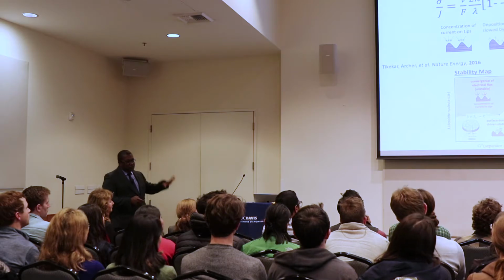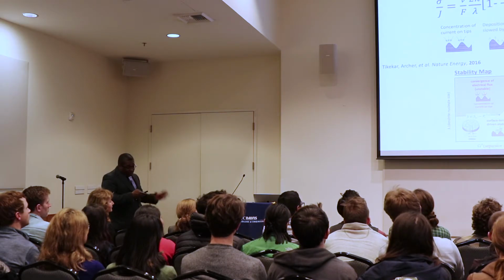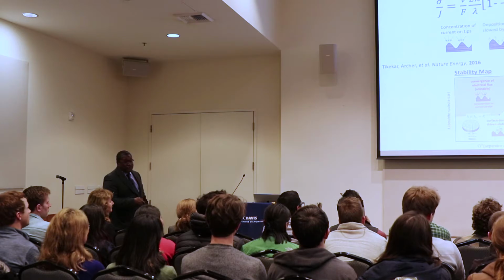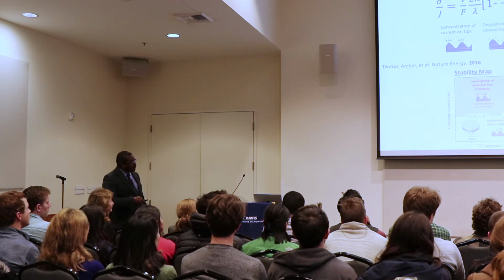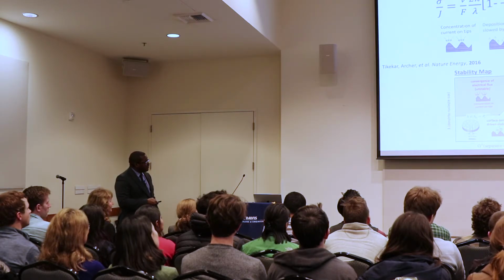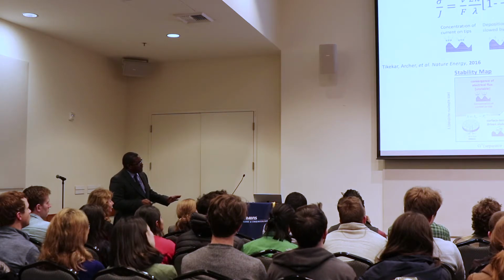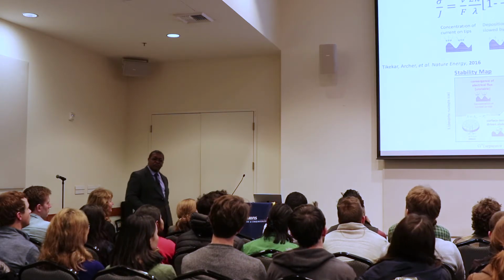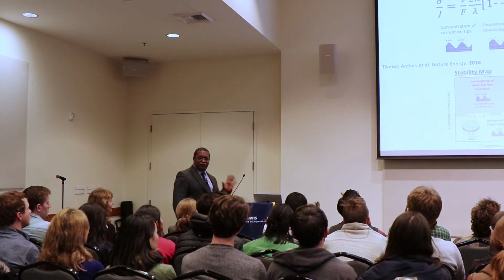It is saying that under the conditions of this model, you can stop the bumps from growing once you keep things small, once you keep them below this critical dimension, lambda CR, that is set, in fact, by this dimensionless group Pi 2. So that's kind of a nice testable result.